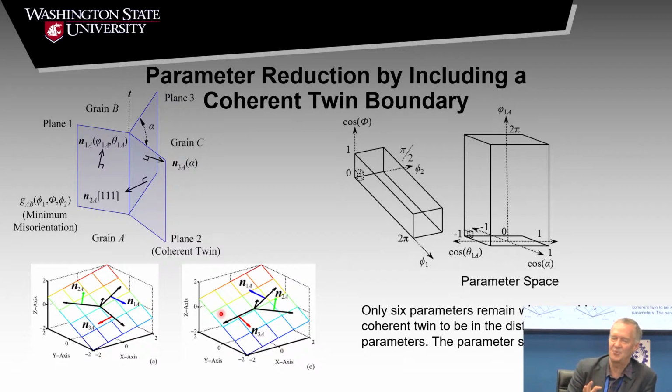So that's 5 parameters of the distribution that you already know. Okay? So out of that 11, I have 5 that are known. I'm down to a 6-dimensional space. Now he only needs 10 to the 6th measurements. He said, okay, I can do 1 million measurements. No problem. Okay? Maybe he did 2 or 3 million, but we can do that.